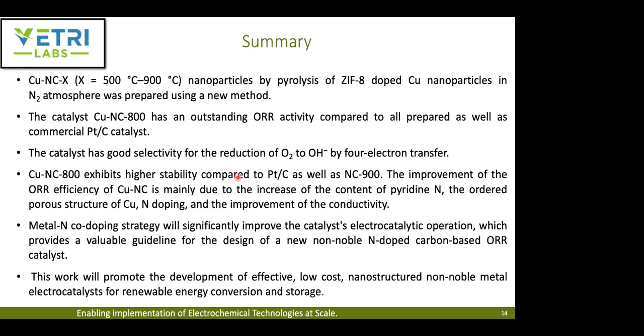And this improvement, they say it's because of the high pyridinic nitrogen and also the ordered mesoporous and microporous structure, and also the improvement in the conductivity and in the rich nitrogen doping. So this way, basically the metal nitrogen co-doping strategy will significantly improve the catalytic performance.